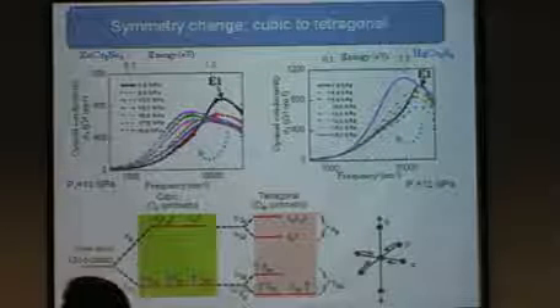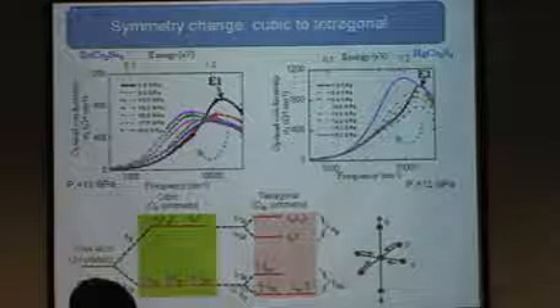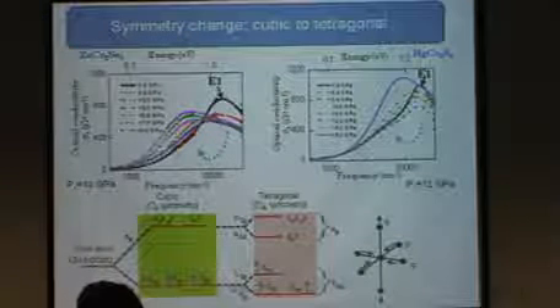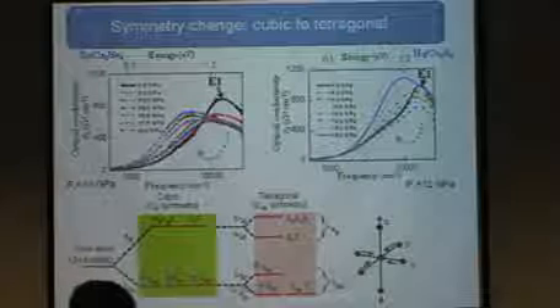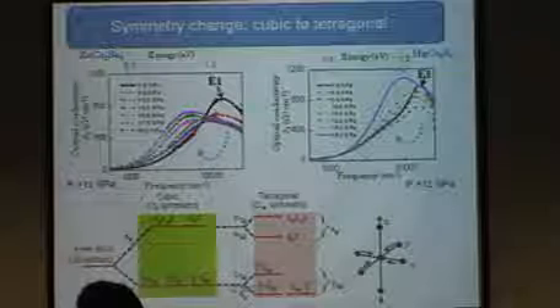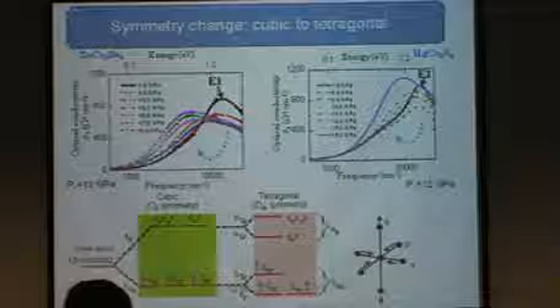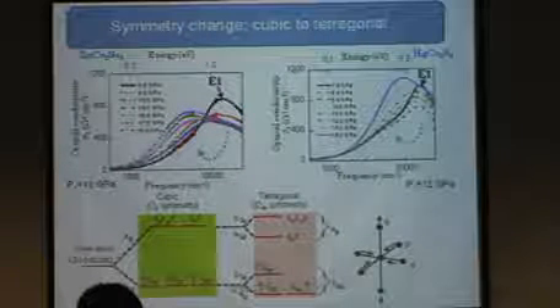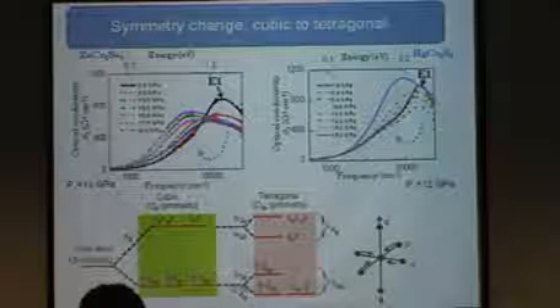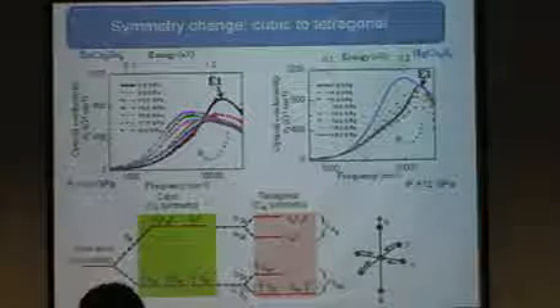Regarding the experiment, this cubic to tetragonal transition will be visible only when you have a single crystal. Am I right? Not necessary. So how can I visualize that you are applying pressure from all sides, equal pressure, isotropically, and you get a phase transition? Yes. Okay. Can you get this effect in polycrystalline samples? Yes, yes, you can get it. For many materials, they do this powder XRD, and then they see how the atoms change, and then they find what is the right lattice symmetry.